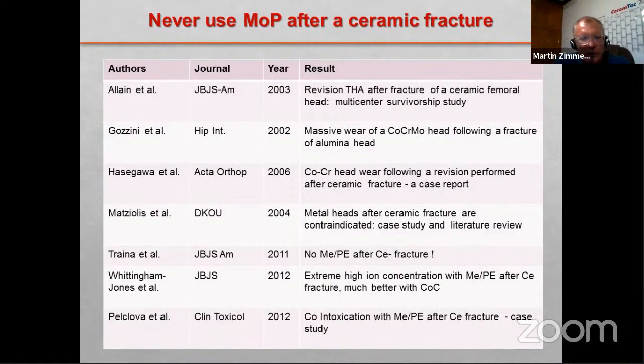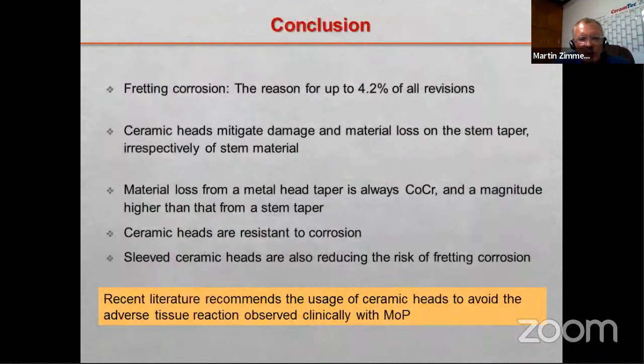So this brings me to the conclusion of my presentation. You have to remember that fretting corrosion occurs in up to 4.2% of all revision cases. Ceramic heads can mitigate the damage, and the material loss comes mainly from the stem taper and is independent of the stem material.